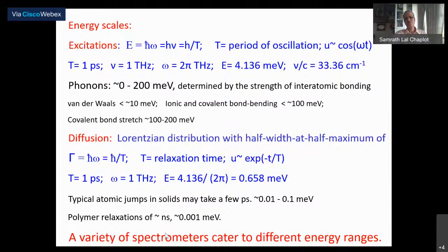In fact, you would know that relaxation times which are in excess of about 10 nanoseconds are probably more easily measured by nuclear magnetic resonance, the NMR technique. Neutrons are for typically faster dynamics. So that will be at the boundary of, or at the interface of, what you can do with NMR. Neutron scattering is typically much faster. It's the nanosecond to picosecond range, and that is where the neutrons would be more meaningful.